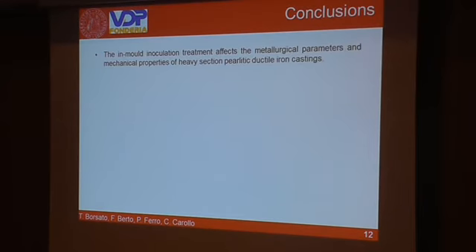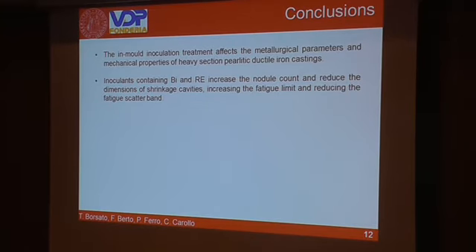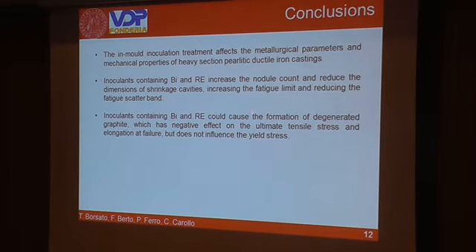So, in conclusion, the in-mold inoculation treatment affects the metallurgical parameters and mechanical properties of heavy section pearlitic ductile iron castings. The inoculant containing bismuth and rare earths increases the nodule count and reduces the dimension of the shrinkage cavities, increases the fatigue limit and reduces the fatigue scatter band. But it could cause the formation of degenerated graphite particles that have a negative effect on the ultimate tensile stress and elongation at failure, without decreasing the yield stress.